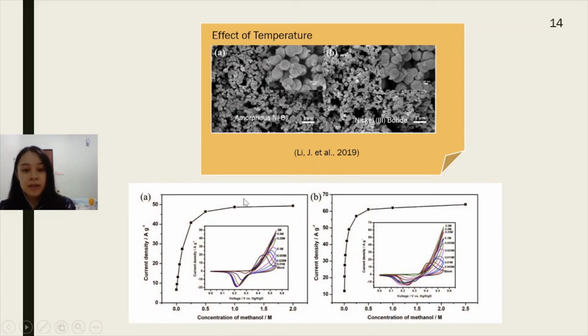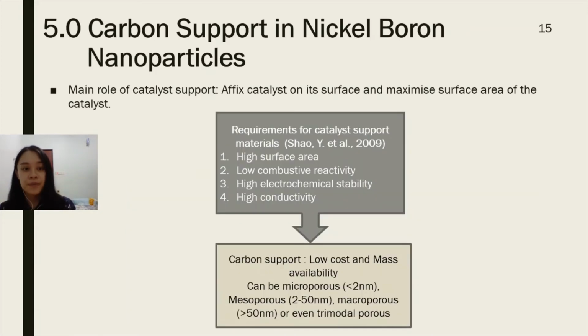So now we'll be looking at the effect of temperature towards the electrocatalytic performance on methanol oxidation for nickel boron. We can see that from the SEM result here, amorphous nickel boron and nickel boride actually doesn't have any much differences. However, the current density actually increases from 45 to 65 ampere per gram after the nickel boron nanoparticles have been annealed. So this actually shows that the electrocatalytic performance of nickel boron towards methanol oxidation actually increases after nickel boron have been annealed. So now we'll be talking about catalyst support in nickel boron nanoparticles.